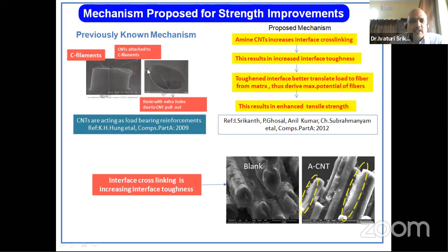the reason for this marginal improvement is, if you see globally in 2009-10, all the publications used to say that the nanotubes that we add to the carbon epoxy composite act as anchoring sites. You can see here, this is a conventional carbon fiber, and these are the small filament structures at the interface. They are carbon nanotubes, and this is the matrix system from which they got pulled out. You can see the hollow zones from where these nanotubes were pulled out.